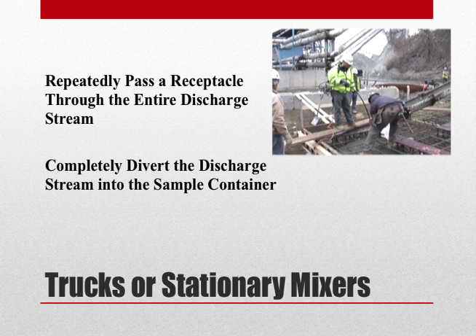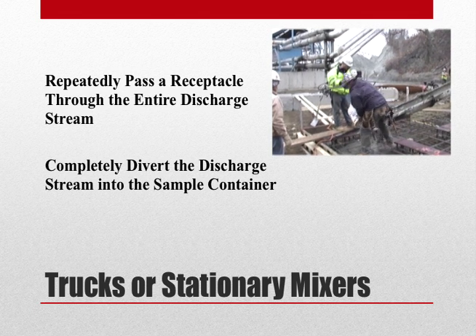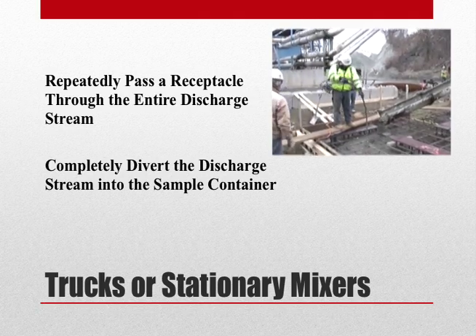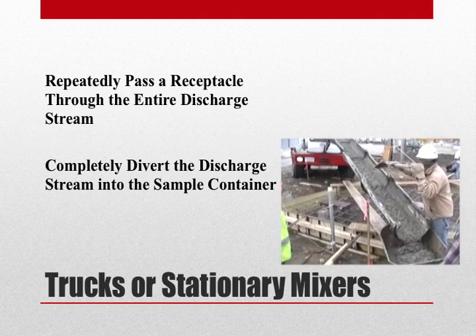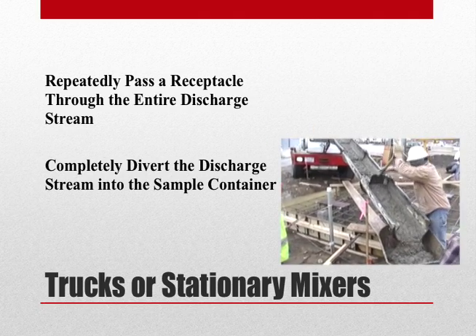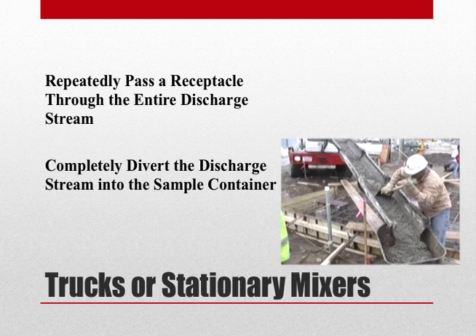For trucks and stationary mixers, the sample is taken by repeatedly passing the receptacle through the entire discharge stream, or by completely diverting the discharge stream into the sample container.